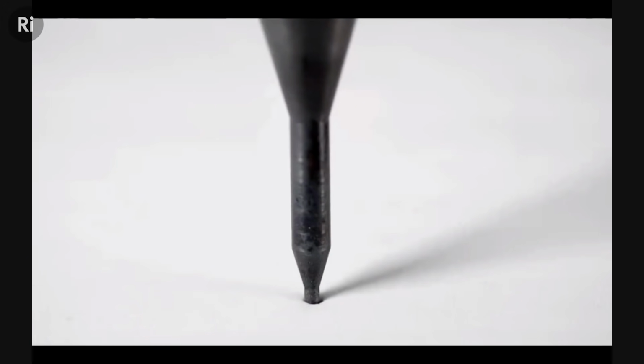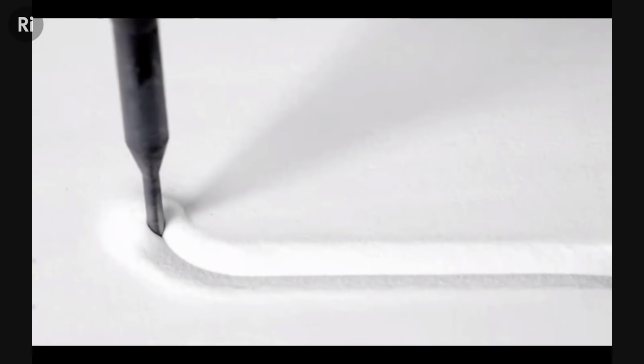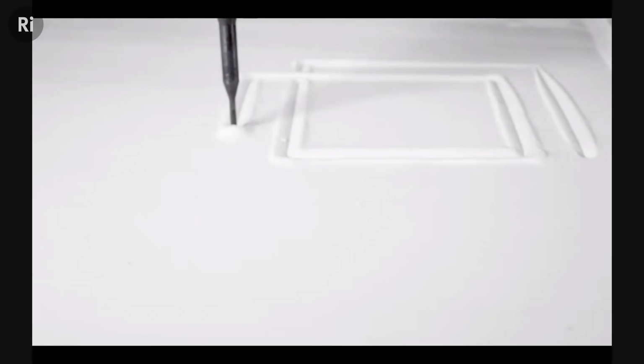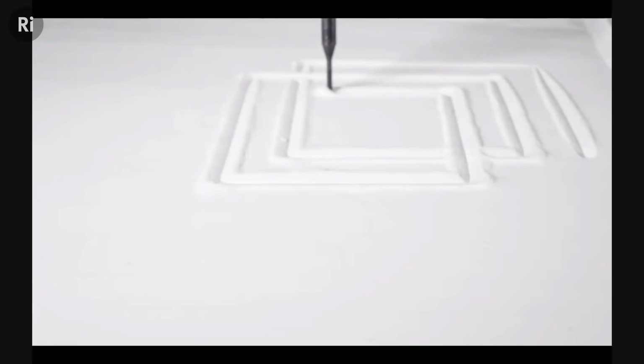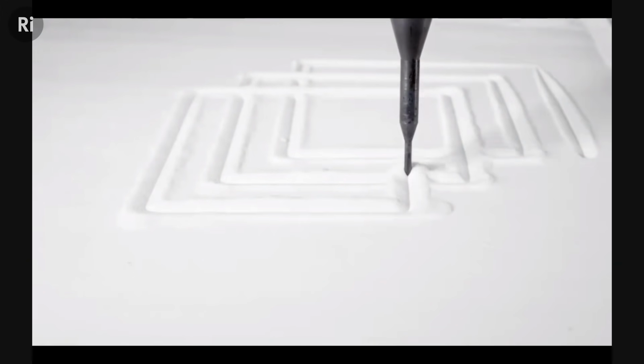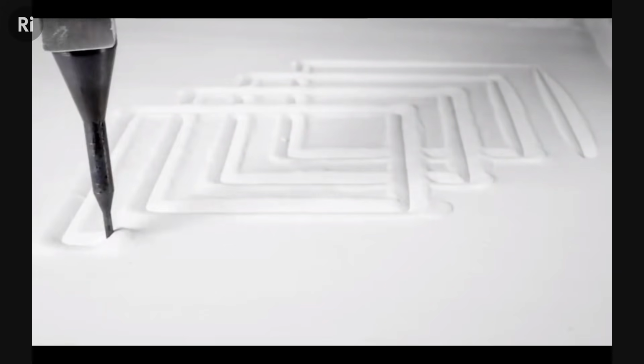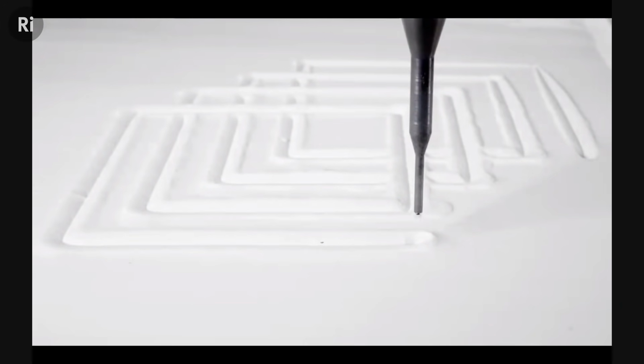After looking at that printing process, we realized one of the challenges is high temperature materials. So we could print chemically curing materials or low temperature. So then we developed a similar process where we print with molten metal. So high temperature metals, literally liquid metal that we print within a powder bed. And the powder bed is very much like the gel bath. It supports the material, so there's no support. And this is even faster.